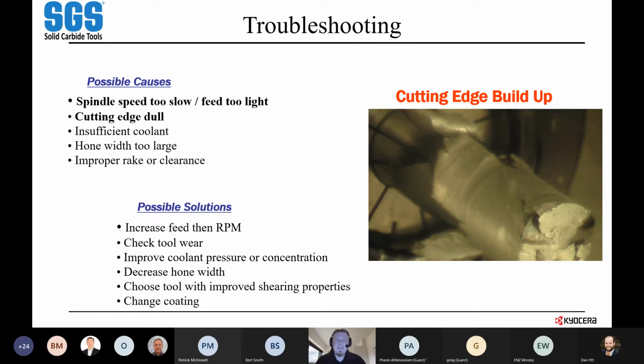And ultimately, when you see this kind of buildup, it's generally going to be a result of your spindle speed being too low or not feeding hard enough, coupled with a dull cutting edge. Coolant plays a factor in it. Sometimes the cutter geometry, like the hone, will be a factor as well as not having the right rake or clearance or whatnot. But generally, it's going to boil down to rates, a dull tool, or not having coolant where it should be, or air even where it should be.